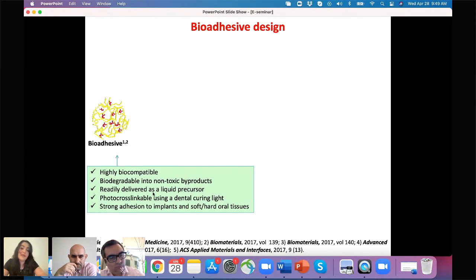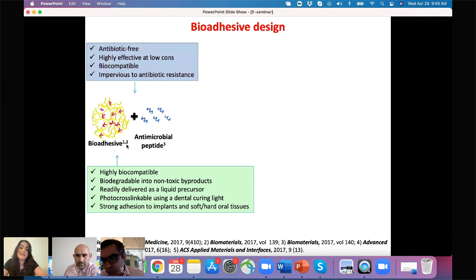is biocompatible. It can degrade into non-toxic byproducts, and we can deliver it as a liquid precursor solution around the implant, and then we can photocross-link it by using a dental curing light. Once it's photocross-linked, it can have strong adhesion to both the implant surface and also to the soft and hard oral tissue. Once we form our bioadhesive formulation, to make it antimicrobial we combine it with our antimicrobial peptides. It can be used as an effective antibiotic-free approach.